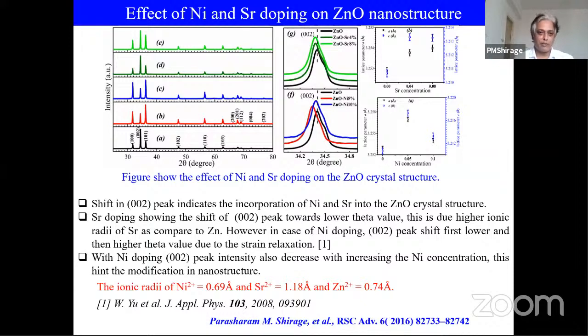Basically, we measure the X-ray pattern, then compare it with the standard JCPDS data. If your measured XRD pattern and the standard JCPDS data match each other, then your material is pure. If extra peaks appear in the X-ray pattern, then you have impurity peaks, impurity material in your material. And once we study this, the first important information we get from X-ray diffraction is phase purity.